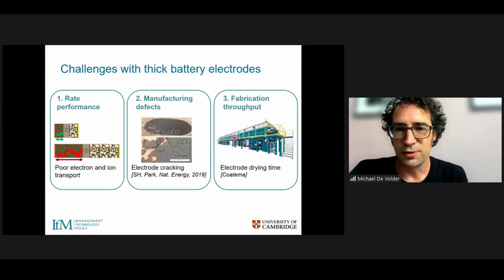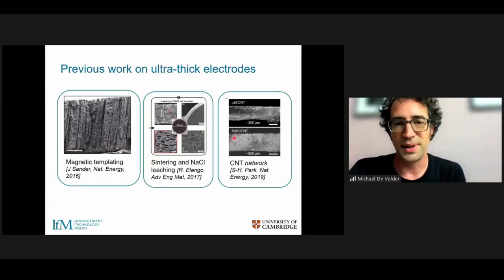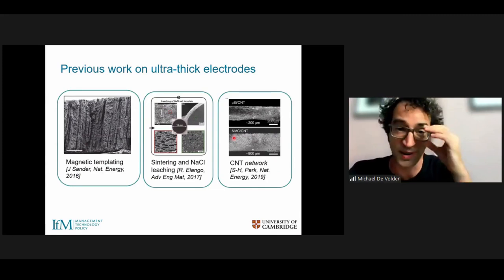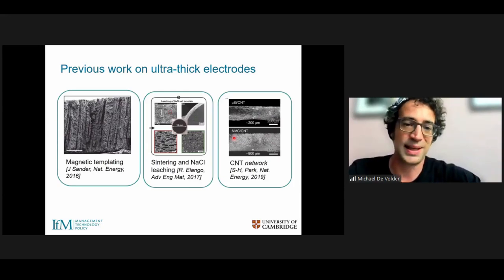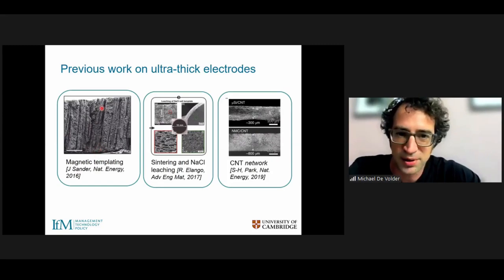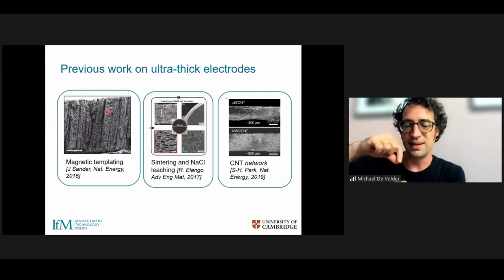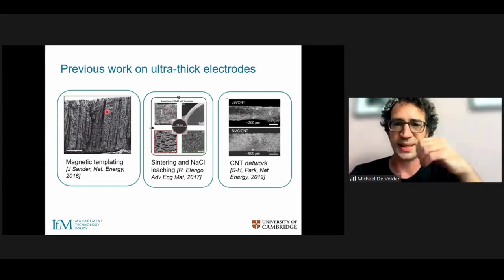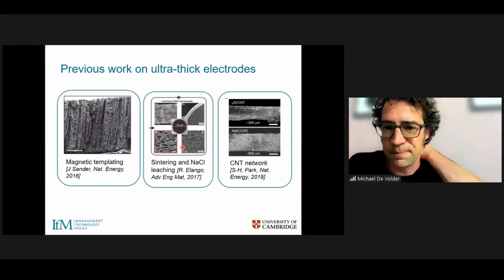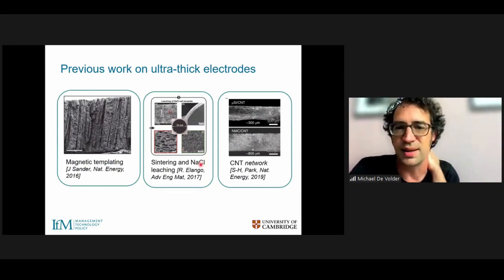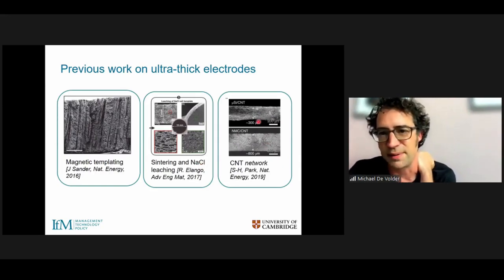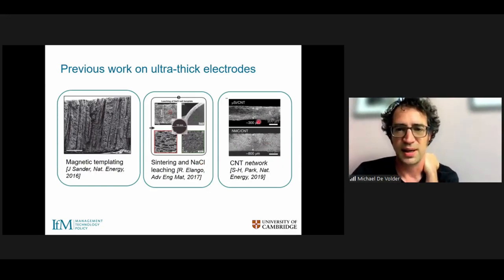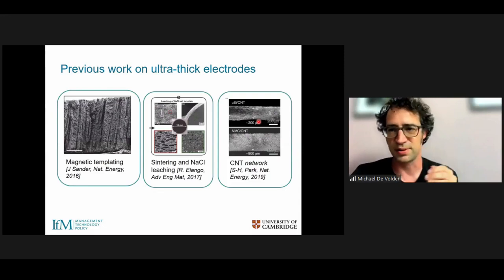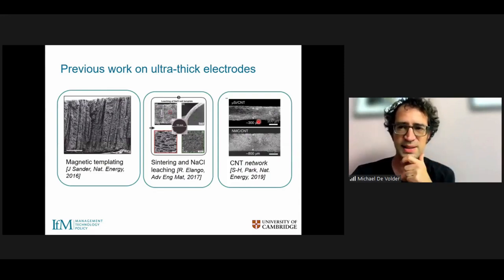Now, different groups at universities have started working towards thicker electrodes. And you can see, for instance, here on the left-hand side, that people have used magnetic particles to create long channels in thick batteries to help lithium ions go in and out. In the middle, people have used salt templating methods to make electrodes. On the right-hand side, people use some advanced carbon nanotube networks. And whilst this work is very interesting, it's not compatible with the sort of large-scale manufacturing processes I described.